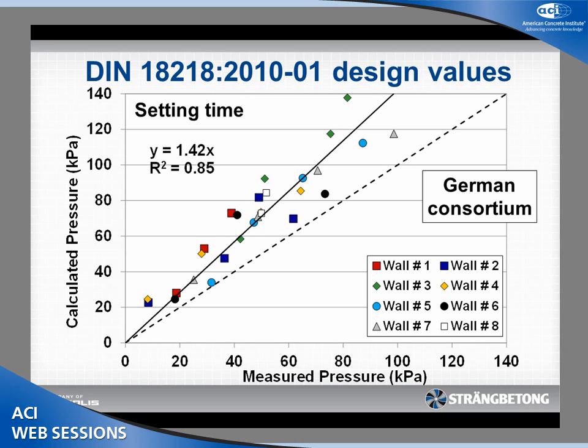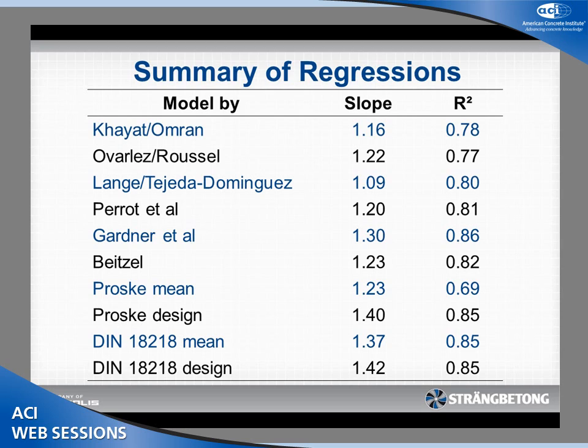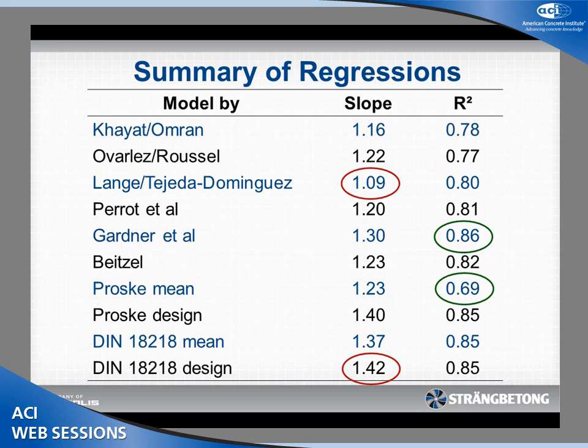To summarize the regressions: we can see that all 10 models are conservative. The slope goes from 1.09 — very close to one-to-one — to 1.42 for the design values of the DIN norm. The R-squared values go from 0.69 to 0.86. So how to pick the best and how to exclude anything? Impossible. And that is one of the conclusions.